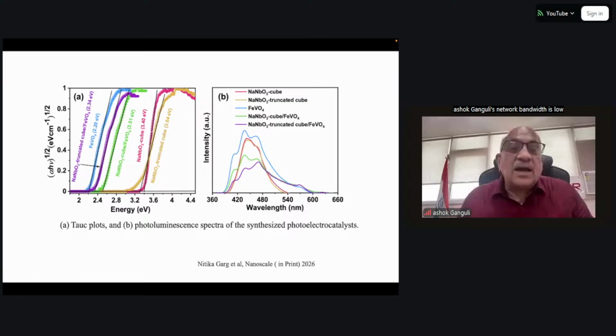The band gap was 3.04 for the truncated cube, and for the cube it was 3.40, which goes down to 2.20 in the truncated cube FeVO4. Okay, something close to that. So you can reduce the band gap from 3.4 to 2.2 in this truncated cube by coating with iron vanadate.